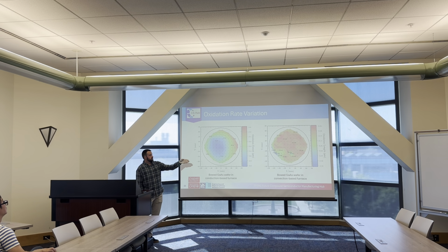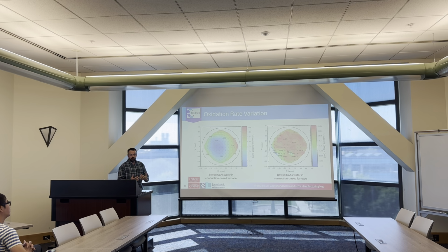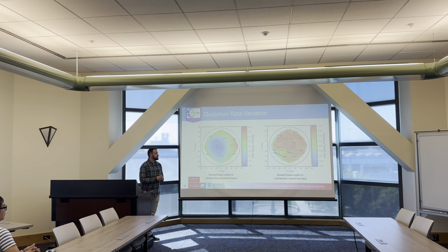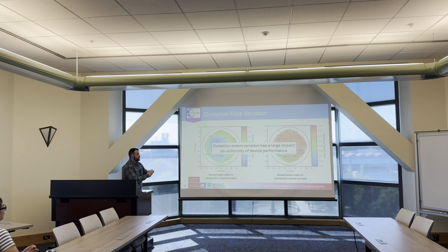But then you can use a method of oxidation that relies on just the ambient temperature, so a convection-based furnace, and those will give you a much more uniform temperature distribution across the wafer, and therefore much more uniform oxidation length variation. And I should just say that the oxidation extent variation has a big impact on the device performance: threshold current, output power, series resistance. Did I say oxide aperture or output power? I meant output power.